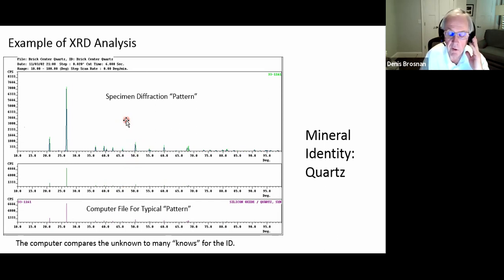So X-ray diffraction analysis has a limit of detection of about 1%. Okay, so if you have something present that's there below 1%, you probably have to use another method to figure out what it is. Now, when I was a student, we didn't have the computers that we have today, so we had to get a pattern on a machine and compare it to index cards that had diffraction patterns on them. There was a little system of doing that, of going to the major peak, the highest intensity peak, and then figuring out what all these other peaks were. But it was laborious and less accurate. So computers have made a big difference in the speed and the accuracy of analysis.